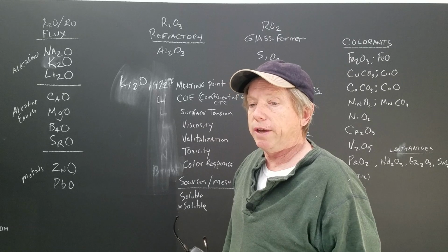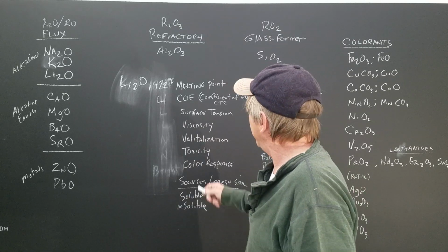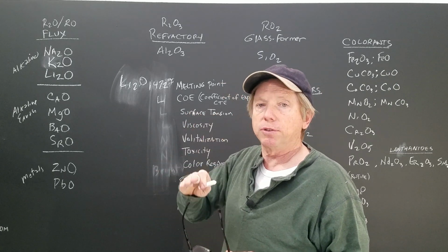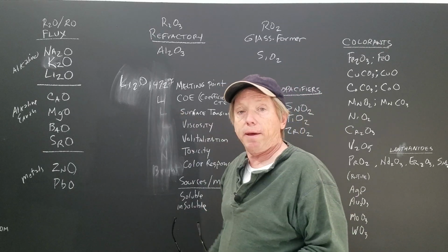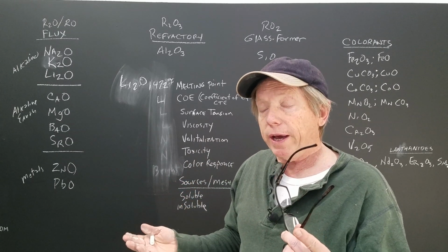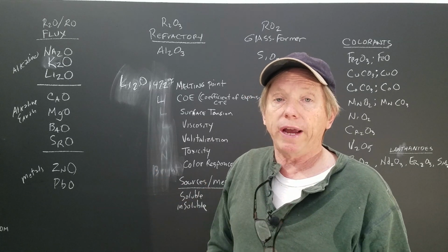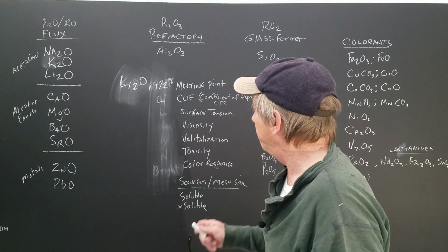So sometimes when you have spodumene or lithium carbonate glaze, they can cause shivering. That's where the glaze sheets off instead of, it's the opposite of crazing. Another, though, advantage of that being low, say you had a high sodium glaze and it crazed, and then if you added some spodumene that's high in lithium, maybe those two would counteract each other and you could cure your crazing problem by doing that.